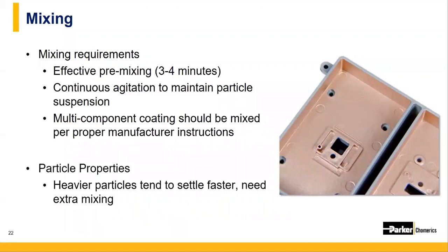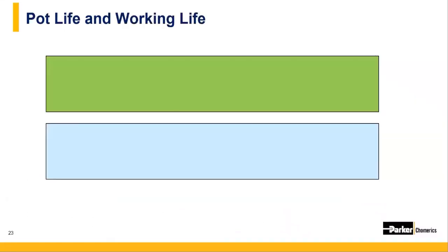So different paints will have different weight particles. Heavier particles will sink faster. Those need extra mixing. But the most important driving factor for the mixing is that if the particles fall out of suspension, the paint will not give you the ideal electrical properties that you're looking for.